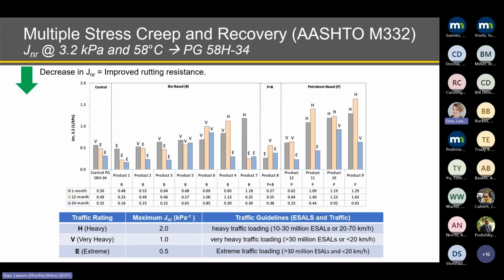Same response observed for the PG58H-34 binder. Again, specifically for this binder that contains a polymer, we see that the maximum solvency of these products was not captured at 1 month, but later on after we reached 12 months of treatment application.